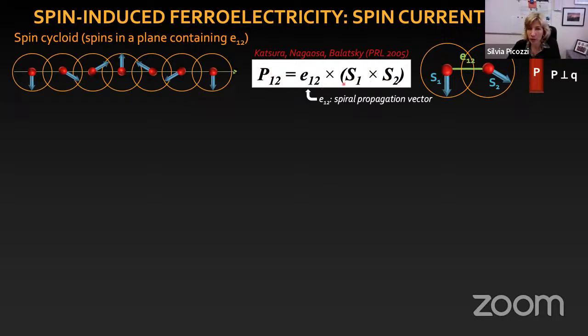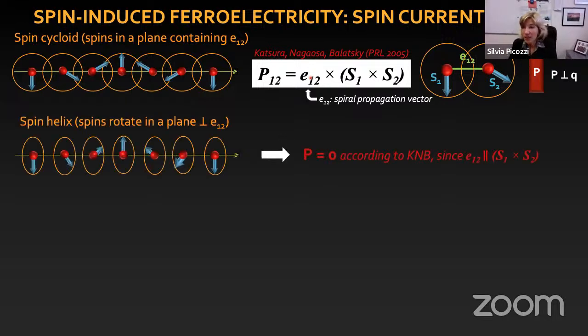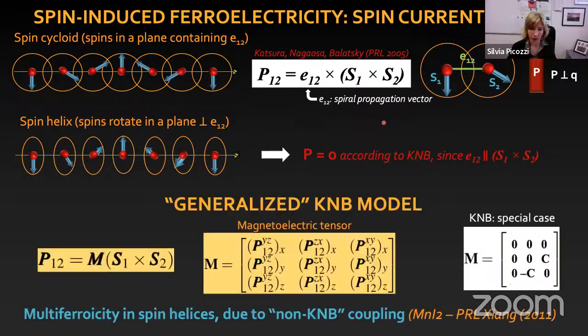It's the cross product of the two spins, times the cross product with the propagation vector. So you have a cycloid like this, what you have in terbium manganite, a cycloid with polarization pointing up. But this also tells us that if you have a spin helix, this bare KNB mechanism wouldn't give any polarization, right? Because it's perpendicular. P is predicted to be 0 because it's perpendicular to the cross product of S1 and S2 times the propagation vector. So we wouldn't expect any P from this bare model.